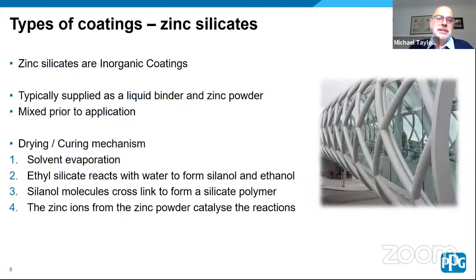So zinc silicate coatings are inorganic coatings, which is a little bit unusual in the coatings industries. Most of the coatings are based on organic resins, but zinc silicates are inorganic. They're typically supplied as a liquid binder, so you tend to get a plastic bottle of liquid and then a zinc powder, and you have to mix them prior to application. In terms of drying and curing mechanism, the solvent evaporation is the first way that the coating starts to dry, and then the ethyl silicate reacts with water to form, I don't know quite how to pronounce it, but silanol and ethanol, and then the molecules cross-link to form a silicate polymer.